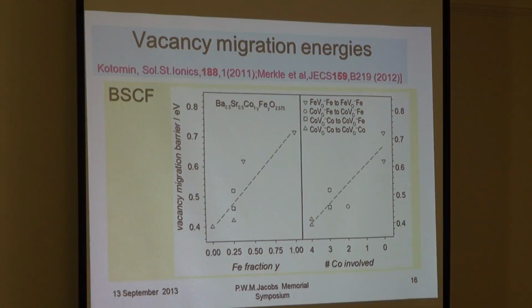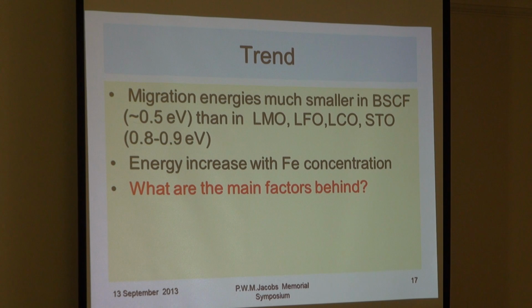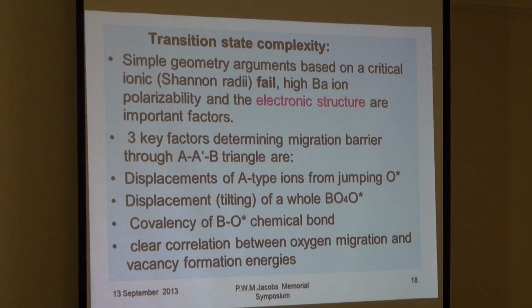which is why there is very fast oxygen vacancy transport. And again, we studied how migration energies depend on the concentration of iron in the composition. And again, we found the same trend. So the migration energy is lowest for cobalt-rich composition, and it increases again almost twice for iron-rich. It's similar to formation energies. So essentially, once again, this material has extremely low migration energy. And we tried also to understand what was the main factor behind these low migration energies.